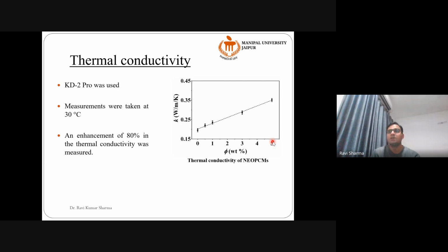But there has to be a limit on the amount of nanoparticle addition. We cannot add more than 5%, as the problem of agglomeration or sedimentation of the nanoparticles will increase. So the addition of even 3% is a lot. Generally 3% to 5% is the maximum amount of nanoparticle addition; we shouldn't add more than that.